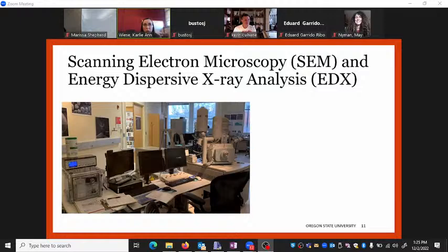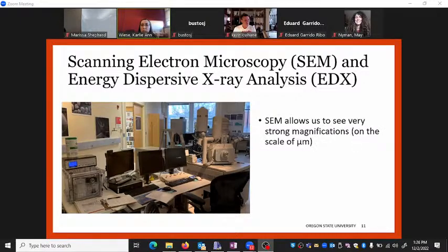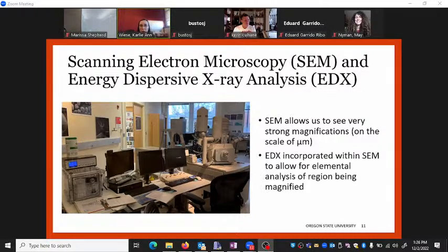Another thing we can do is use scanning electron microscopy, SEM, and energy dispersive X-ray analysis, EDX. SEM allows us to see very, very strong magnification, so we're looking at our materials on the scale of micrometers. And then EDX is incorporated within the SEM, so it allows us to do elemental analysis on the region that we're magnifying.